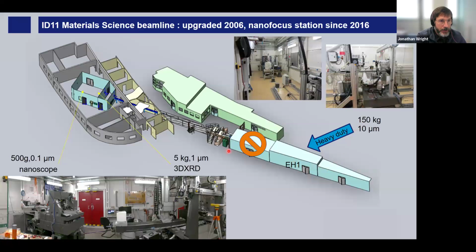Then as we move along the beamline, there was an EH2 hutch here, and this is where the first 3D XRD microscope was built in around 2000. That was a collaboration from the DTU group at Risø. That instrument was moved out to make a long beamline. So just before the phase 1 ESRF upgrade program of making long beamlines, ID11 and ID13 were both made into long beamlines, and this 3D XRD station was moved out to be further away from the source. So this takes samples up to about 5 kilograms, and now we can reach around 1 micron of spatial resolution.